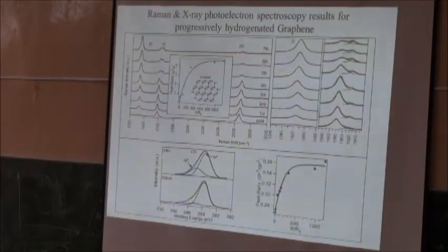And this 2D band has pretty much disappeared, right? So this is very strong evidence for making the sp3 structure, because this corresponds to the sp3 Raman band. So this is very obvious. So we actually analyze this band. We just plot separately. This band I plot here, and this band I plot here, and you can see how they. Yeah. We have a question.